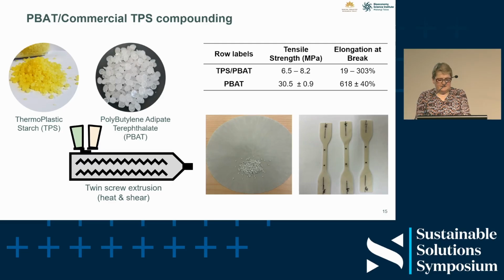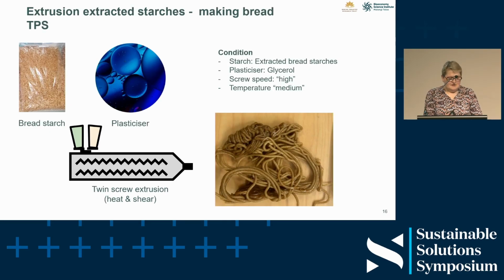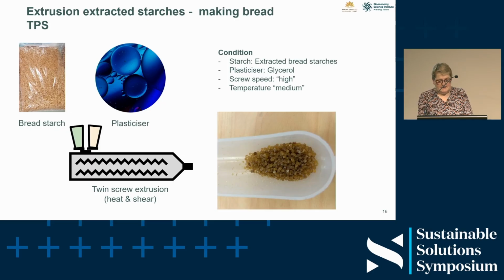By doing this with the commercial thermoplastic starch, we basically established the conditions for copolymer compounding to achieve the mechanical properties we required for a bagging application. Then came the fun bit, where the process was applied to the bread thermoplastic starch. And like any good science project, it didn't immediately work, but with a bit of tweaking, that's the extruded material, we actually ended up with nice little bread thermoplastic starch pellets. So that was a success.